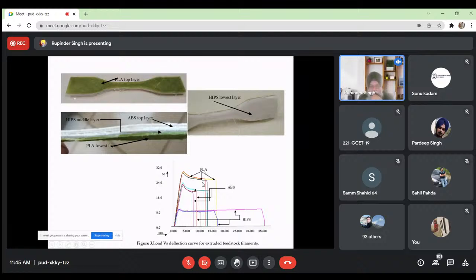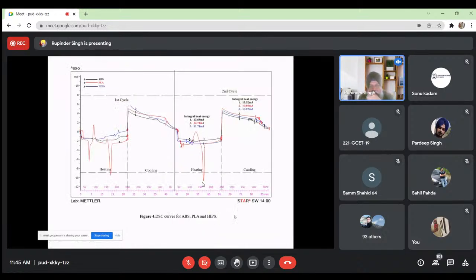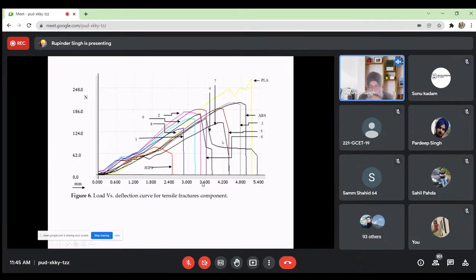Once I have a single material tensile coupon, like for the PLA, similarly for the ABS, similarly for the HIPS, we also did their thermal analysis, like heating and cooling cycle. And what we observed is that PLA was the most thermally unstable material as compared to the rest, right? So we tried to see their stress strain curve on a typical UTM, and we tried to establish the area under each curve for getting the value of the modulus of toughness.